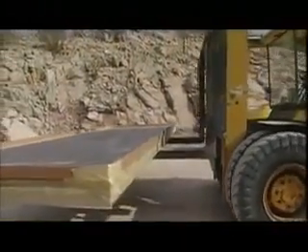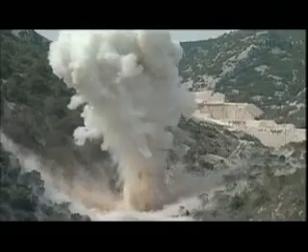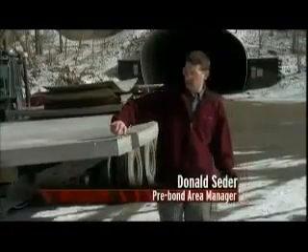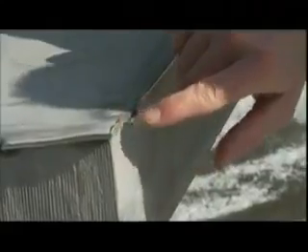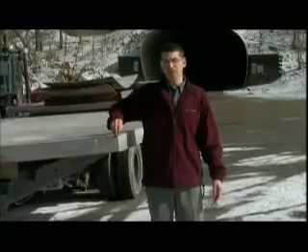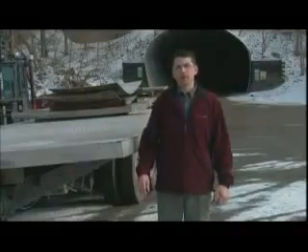To create an explosion weld, two large pieces of metal are stacked atop one another, then covered with a high-powered explosive. When detonated, the downward force of the explosion welds the two pieces together through a combination of intense force and remarkable physics. What you can see here, and it's very clear, you have two different materials. Stainless steel is a darker gray, a lighter gray for the carbon steel material. The detonation was initiated at this point, and you can see the deformation from our initiator. That starts the explosion, and the explosion rolls across the entire top surface of the plate, zipping the two together.